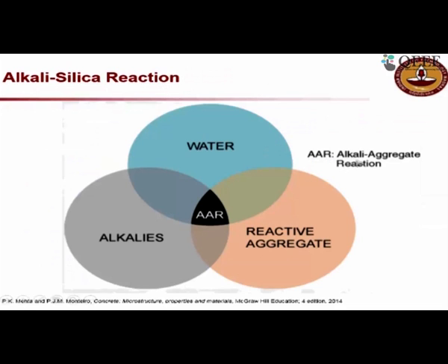Now, a holistic view here: you have to have moisture or water, a sufficient quantity of alkali, and the aggregate should be reactive in nature. Only if all three exist will you have alkali aggregate reaction, or as we call it, ASR, alkali silica reaction, because most of our aggregates are rich in silica. So the three elements required are moisture, alkali and reactive aggregate. If you don't have reactive aggregates in your concrete, then you don't need to really worry about alkali silica reaction. In some parts of the world we don't have reactive aggregate, so we don't have a problem there.